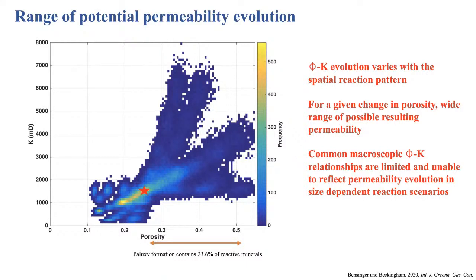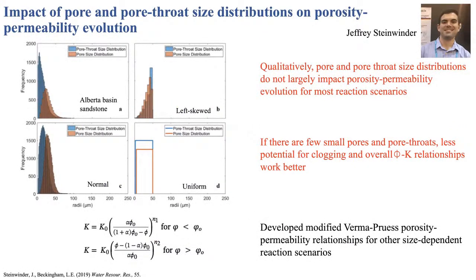And it really depends on the spatial distribution of the reactions. And so sometimes those macroscopic porosity permeability equations work really well, but they're really limited in terms of reflecting permeability evolution for when reactions depend on pore and pore throat sizes. We've also explored the impact of different pore and pore throat size distributions on permeability evolution using a similar kind of approach. We found that qualitatively, that doesn't have a large impact on porosity permeability. We did observe, though, if you have few small pores and pore throats, you have less potential for clogging, and that overall those porosity permeability equations work better.